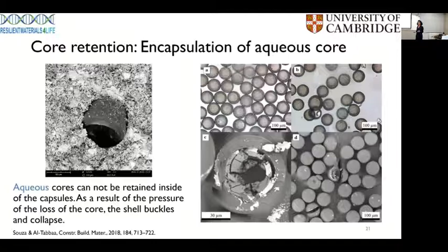Hopefully that's a question you may be asking, but hopefully not, because you've read my paper and you know that it's very tricky to do that. Water is a very small molecule and it's very hard to retain inside the thin shells we are talking about with capsules. Even if you produce a capsule, so this is a double emulsion containing colloidal silica inside, when you dry that material, you just have the colloidal silica retained inside the shell and all the water leaks out of the shell.